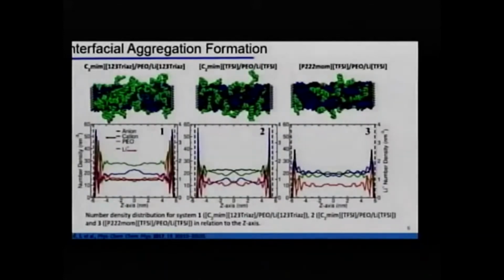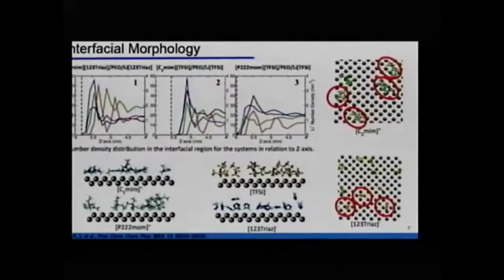And if we zoom in here to see how this distribution looks, we can see this. These three plots are just a zoom in on the interface region from the previous plot. When I say interface region, I'm talking about the lithium metal surface and all the particles within a 1 nanometer cutoff from the surface. Comparing 1 and 2, we see a very similar behavior. These are the systems based on imidazolium triazolide and imidazolium TFSI. Just comparing these two, we can see that changing the anion doesn't change too much the distribution of the particles in the systems.